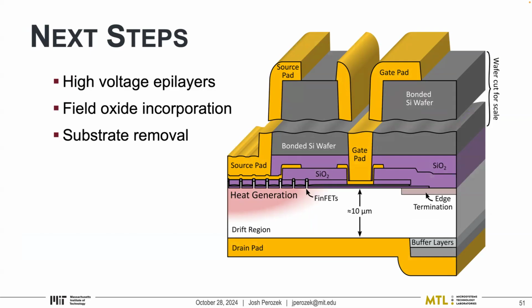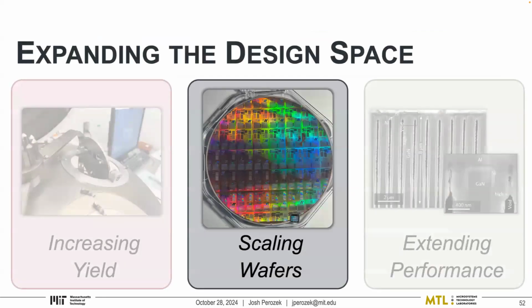But the next steps are really, we want to increase the thickness of the epi layers, actually make this something that can support 600 or 1200 volts. We need to incorporate that field oxide, and then eventually we have to fully remove that substrate that I said was so great for working with because it's not actually conductive. So for a vertical device, you do have to take that off. Those are underway. I hope I can report back to some of you with the results of that. But that has been our efforts on scaling these wafers to an 8-inch platform.